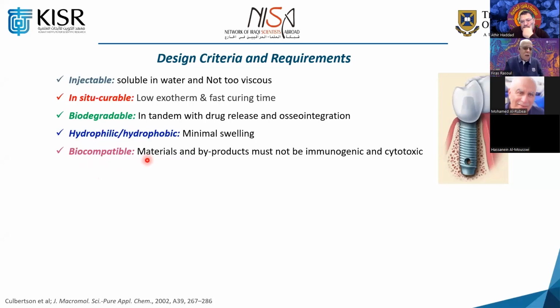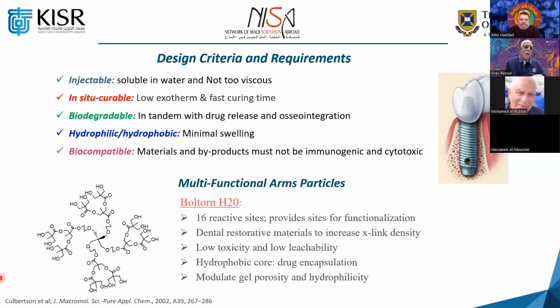Also, it has to be biocompatible. I mean, when it's degrading, you don't want the material or the polymer, or even the other components, to cause any immunogenic response or any cytotoxicity. So it is very important that the material itself and the byproducts after degradation should not be toxic at all. So this is really the design criteria. We have to work within that framework in order to come up with a material useful for that particular application. So we looked into the literature.